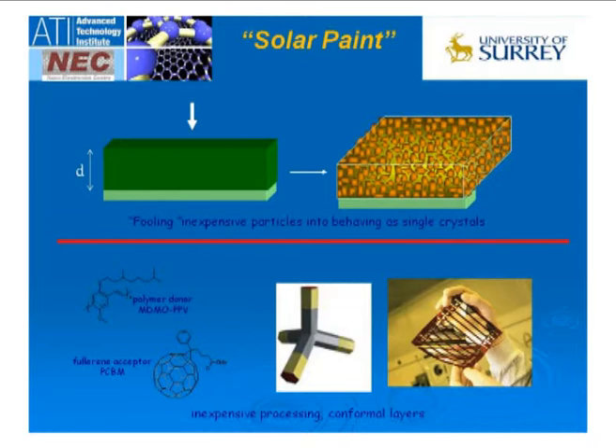We are also trying to use various polymer systems, and in this case, typically you would use something like a fullerene PCBM, a C60 based material, as an acceptor, and you'll have P3HT or copper phthalocyanine or many of the other materials as a donor material. And you're trying to make materials that are solution processable so that you can start making these things inexpensively as paints.